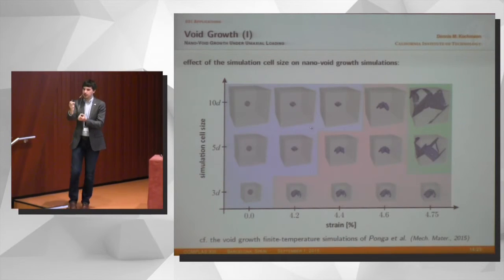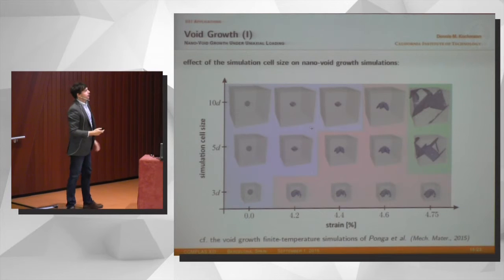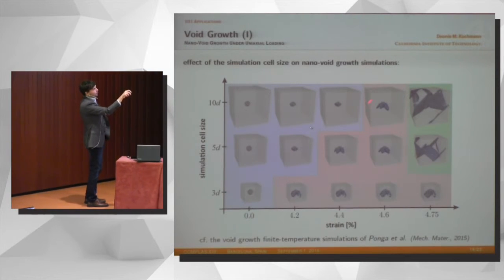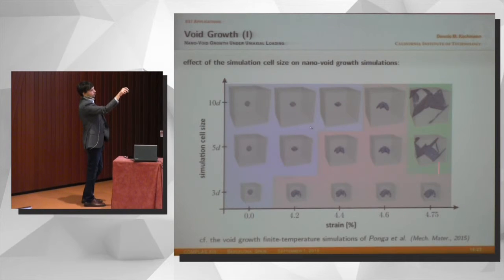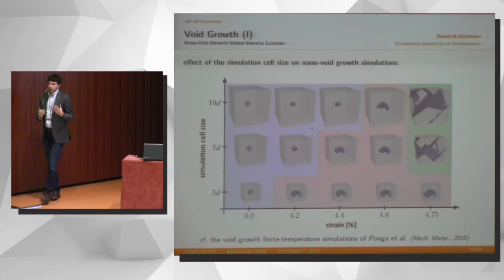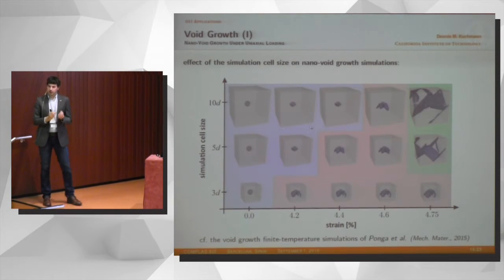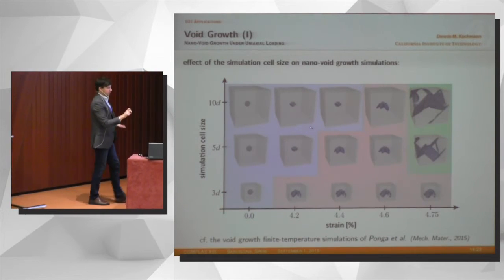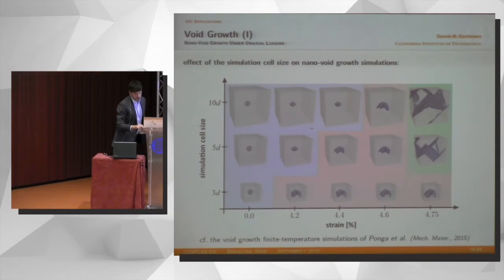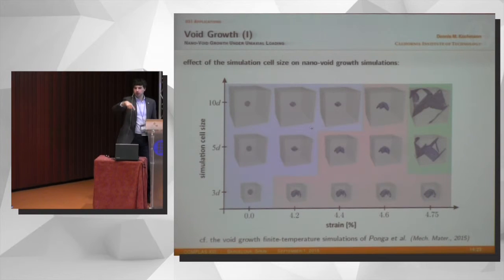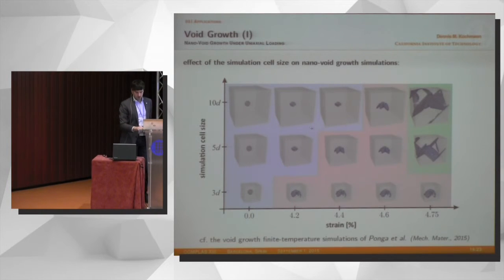Simply, the void is not feeling its neighbors anymore, and so the apparent response is different. And then finally, once it has nucleated, in the bigger cells, they can also grow and move much faster than before, which is not happening down here. And then again, periodicity kicks in. So whenever we run these simulations, we have to be very, very aware of the fact that the cell size plays a crucial role, and we have to be on the bigger side in order to get the accurate response of dilute voids. Otherwise, you're just computing a periodic array, a grid of voids.